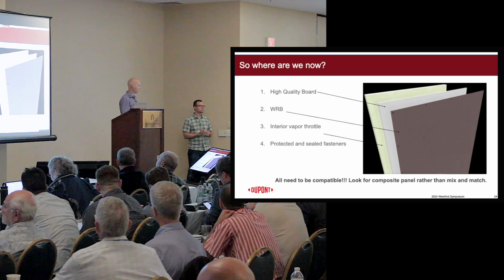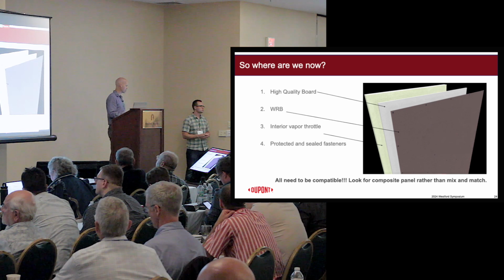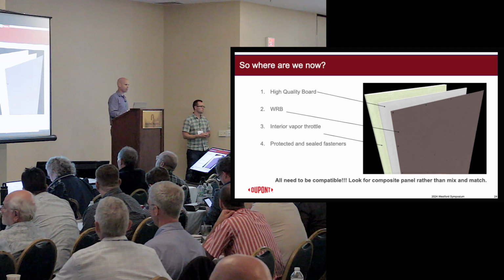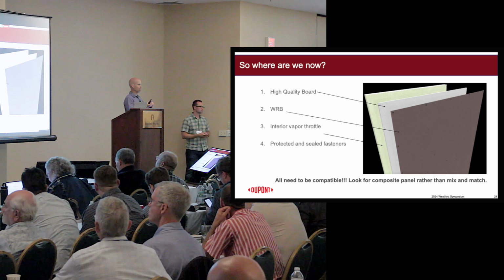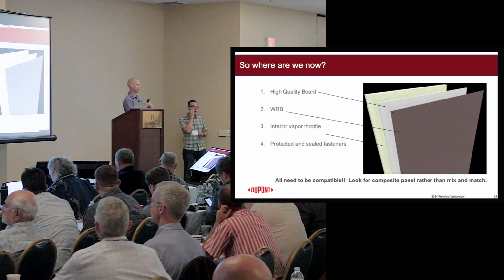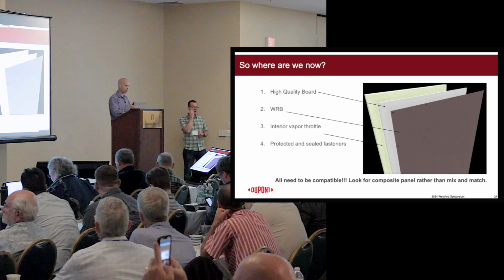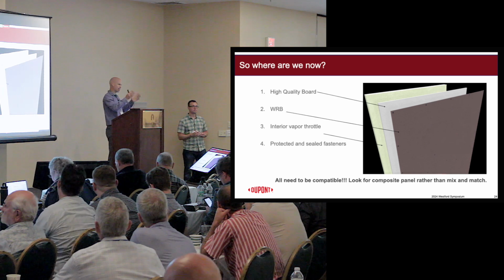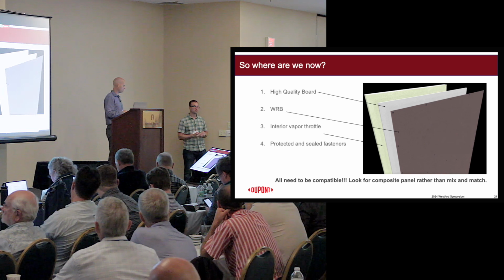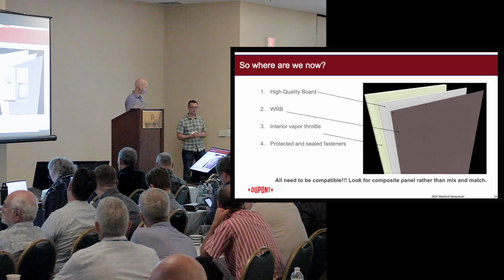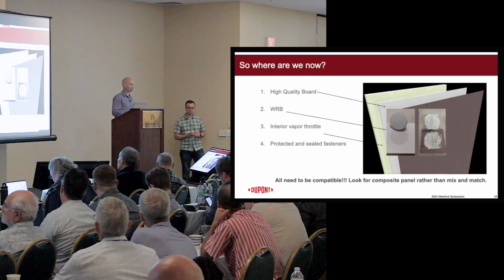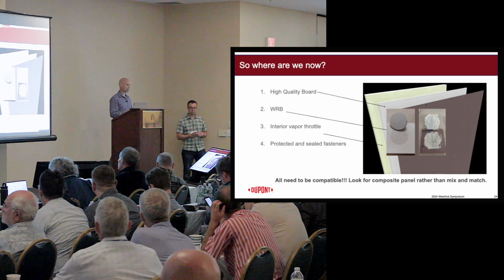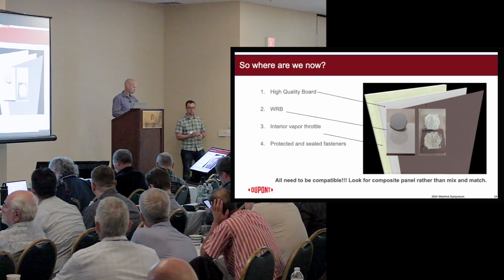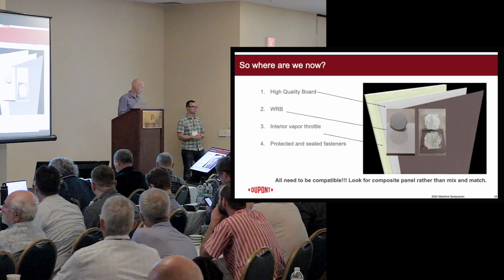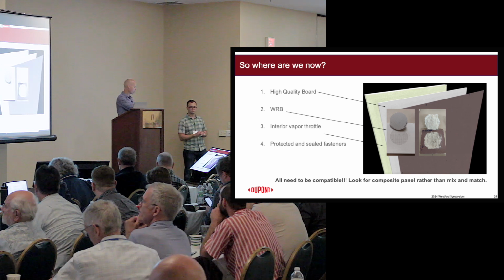You can see the picture on the left, is that adhesive or cohesive failure? Who was listening earlier today? Yes. I love it. Yep, that's an example of adhesive failure. The material just is not sticking, and they separate right at the level of the coating and the magnesium oxide. You can see on the picture on the right, it is cohesive failure of the substrate. You just tore the board apart when you try and rip off the WRB.